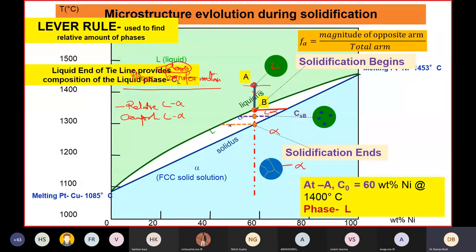What is visible here are what we call grain boundaries, because the solidification is not happening at one point. They are all nucleating separately. Once they nucleate, at this point, when the temperature is lower than the solidus line, you have only single phase alpha, which is polycrystalline.